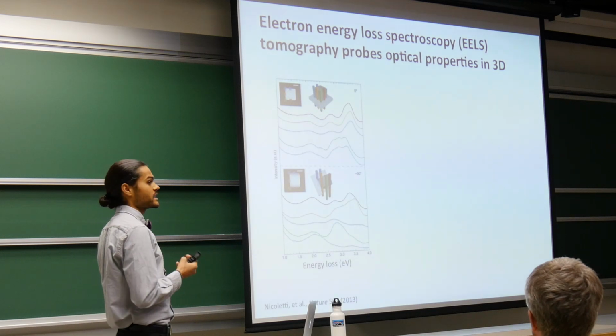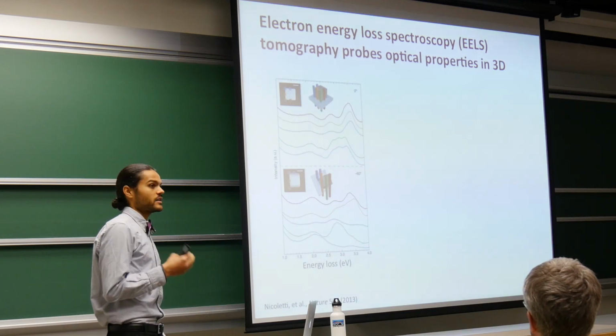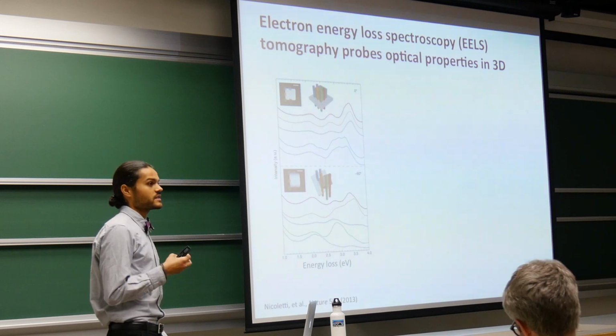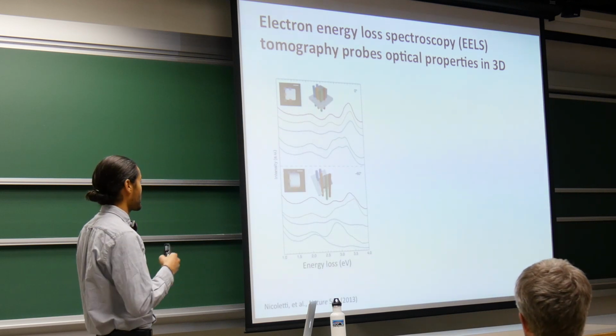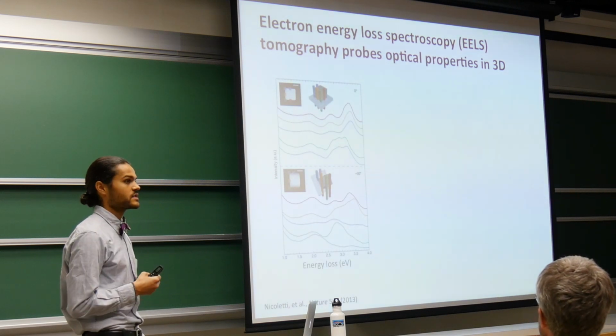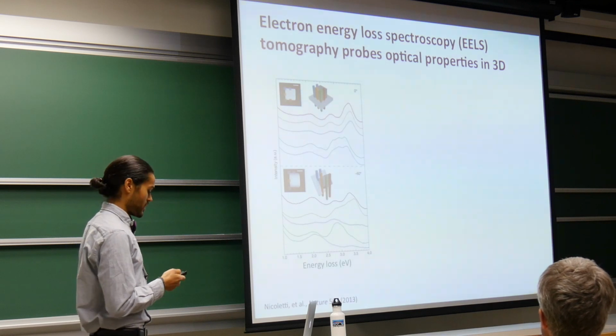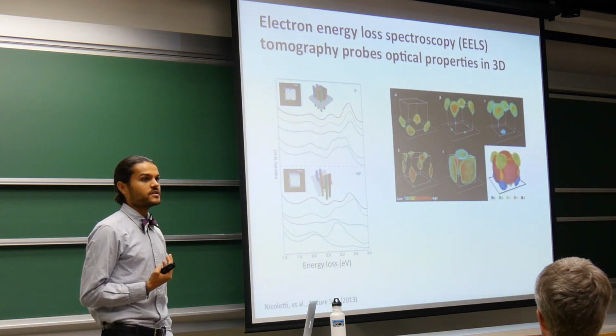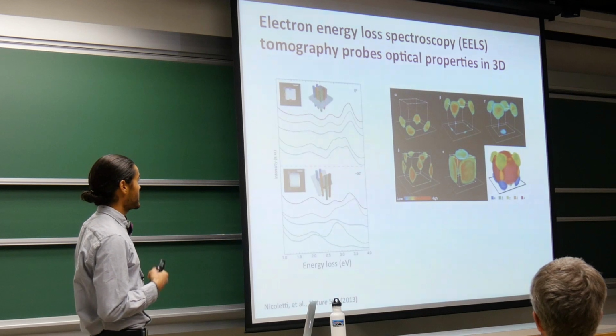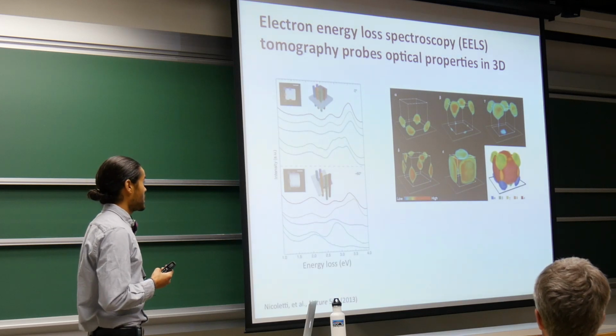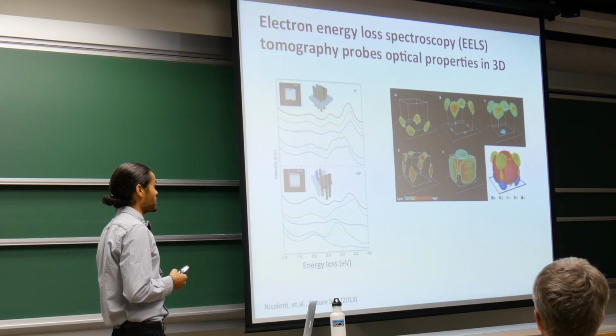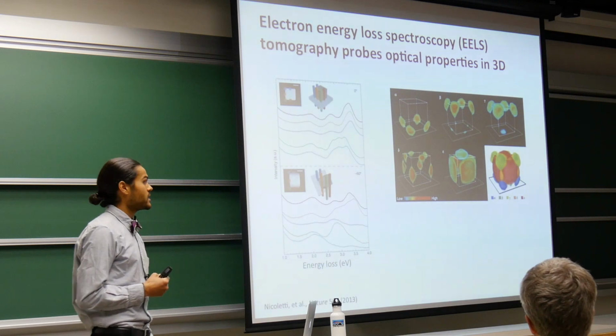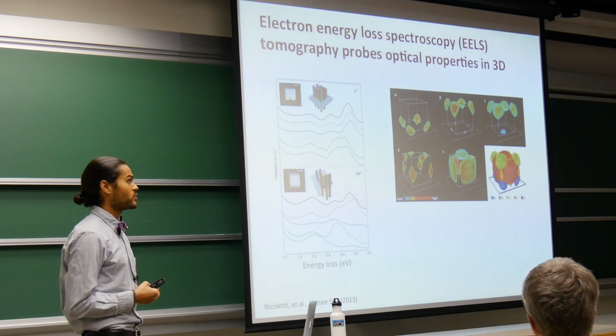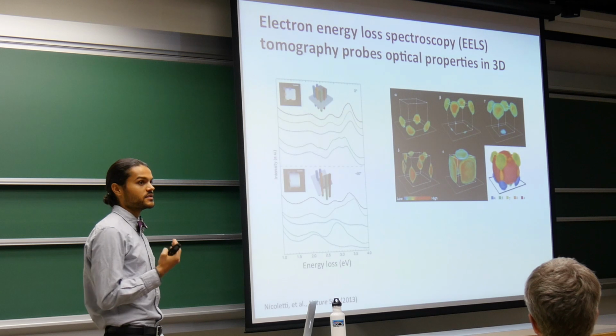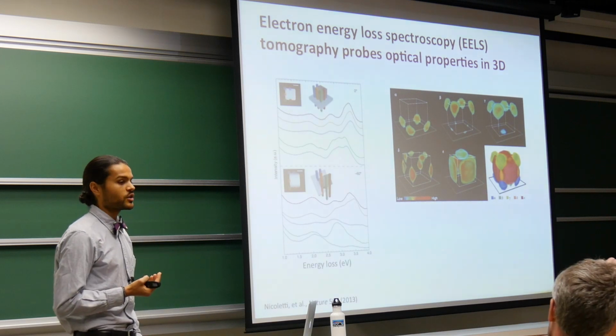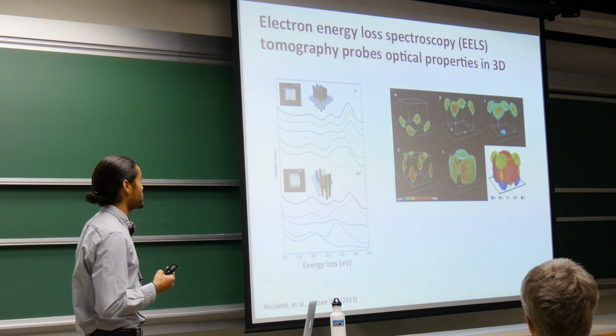So here they were looking at a silver nanocube with electron energy loss spectroscopy, and by tilting the sample and combining their spectra, or their tilt series, with tomographic methods, they were able to generate images related to the localized surface plasmon resonances of this particular system. While this was really beautiful and innovative work, it does have one significant limitation, which is that this particular technique, EELS, indiscriminately probes both radiative and non-radiative properties.